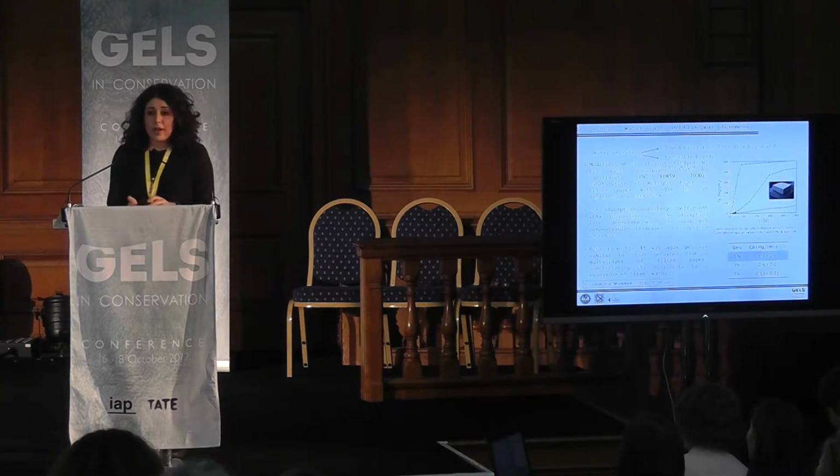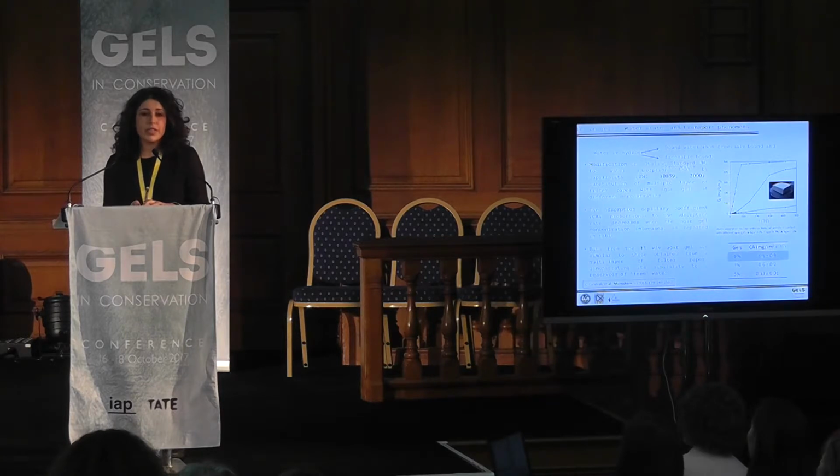An important step of my research, as I said, is the study of the water state. According to the literature, we know that water in hydrogels could be in bound and free form. So it is interesting to understand to what extent the presence of bound and free water could influence the transport phenomena. To do that, we modified the Italian standard for the study of water absorption by capillarity, substituting the multi-filter papers with agar gels at different concentrations.